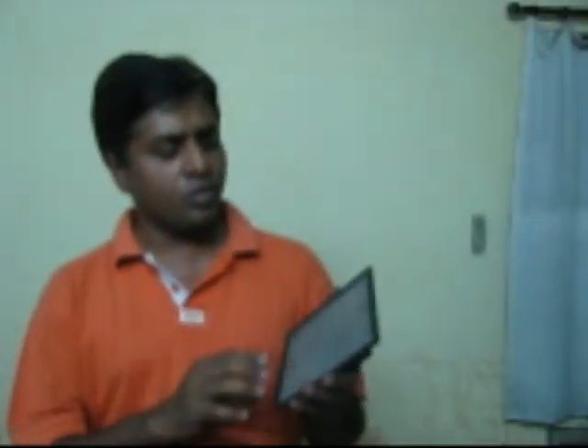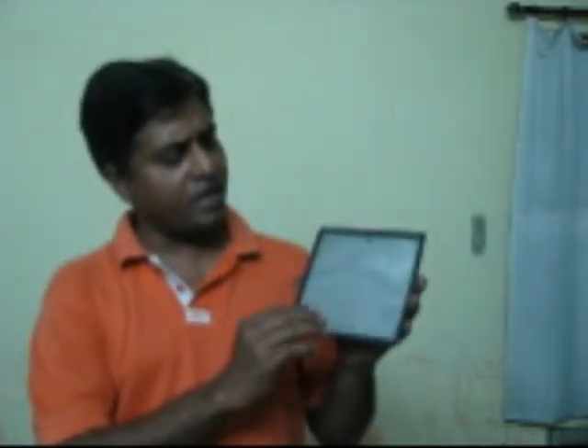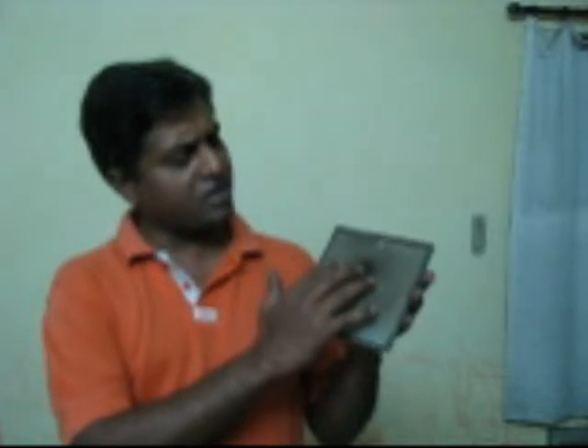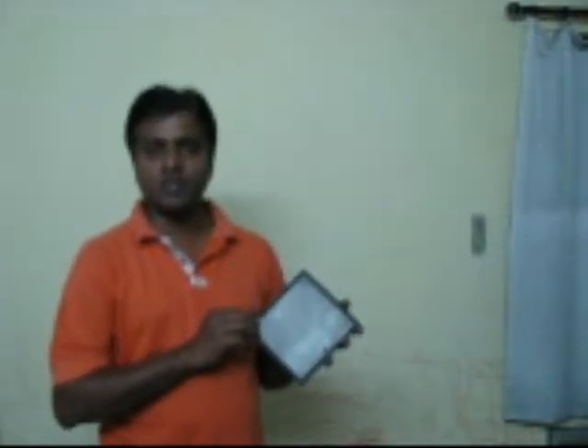This is one of the electrodes made out of the special grade material. You can see the anode side, which is quite clear. On the cathode side, there is a slight black deposit, that too after running it for 2 weeks. You can see a small 4 mm hole for the gas outlet and a 2 mm hole for the purpose of water filling. We have used EPDM gasket all across, which is around 5 mm wide. We have operated the booster made out of this electrode for over 2 weeks and found no discoloration in the water.